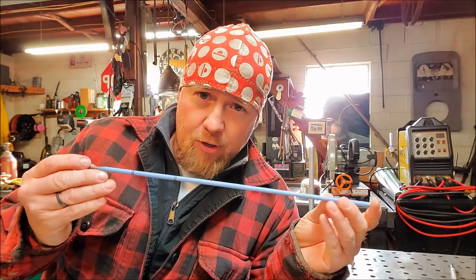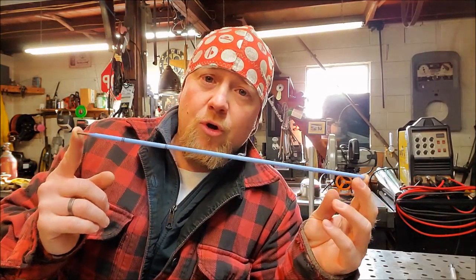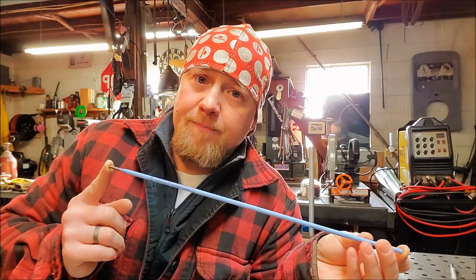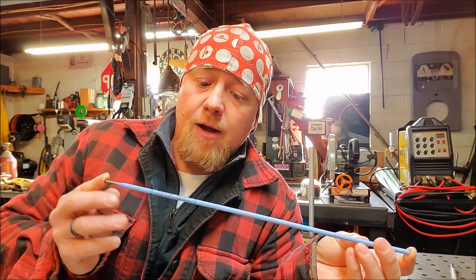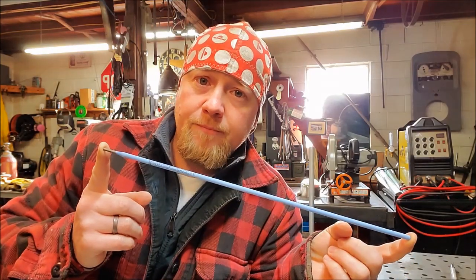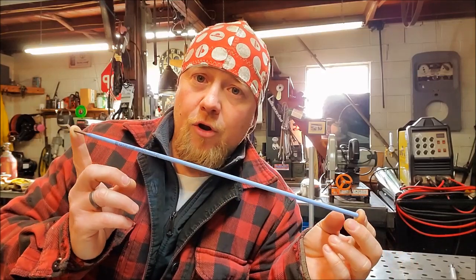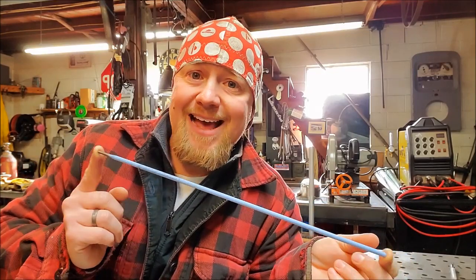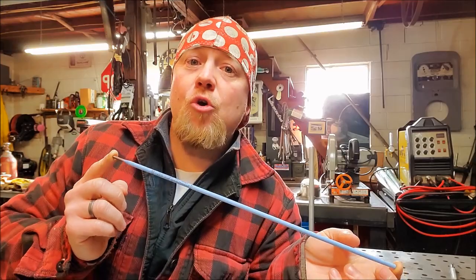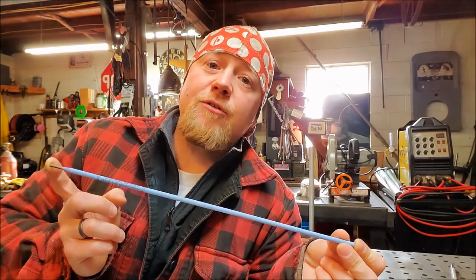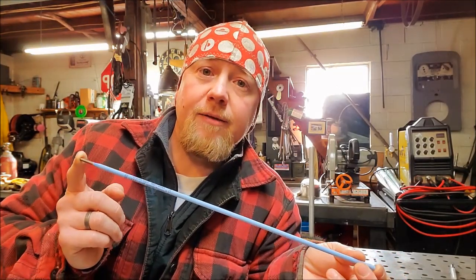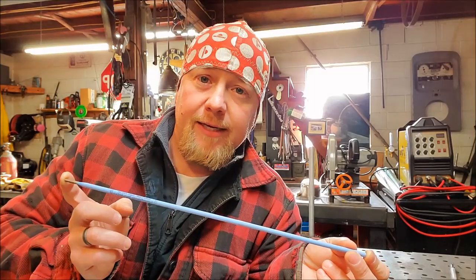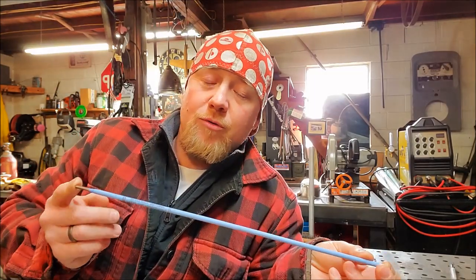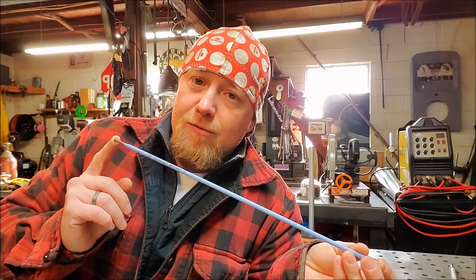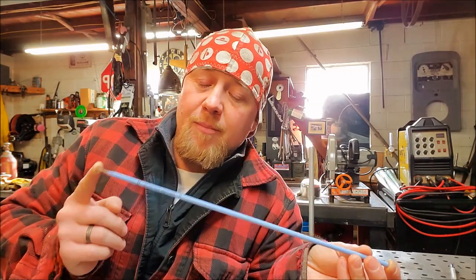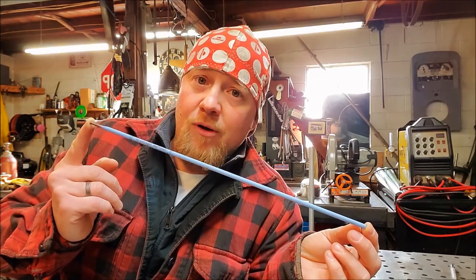So I told you earlier that these rods had chrome in them, nickel chrome. That chromium mixes with the carbon from the cast iron and forms a chrome carbide, which is hard and brittle and equals cracking, things like that. So what you don't want to use these for is cast iron. Obviously not aluminum either. But anything else, you can weld it with these.